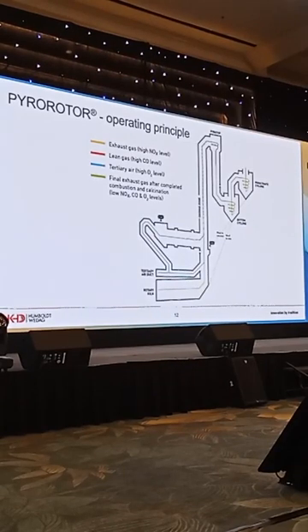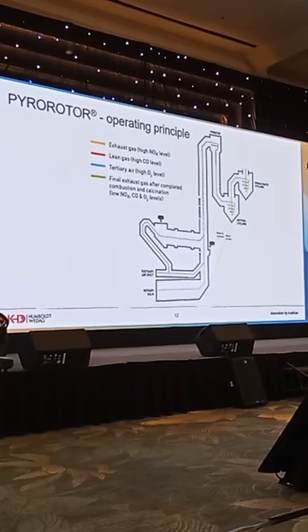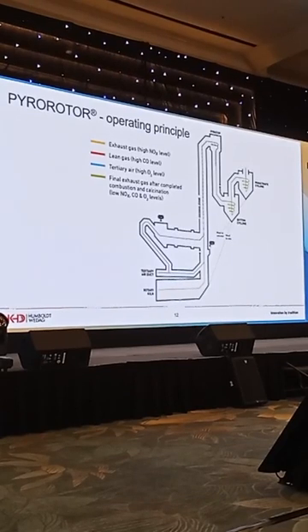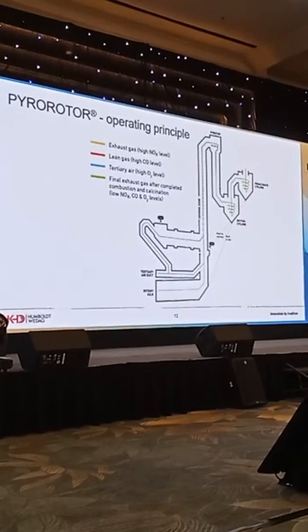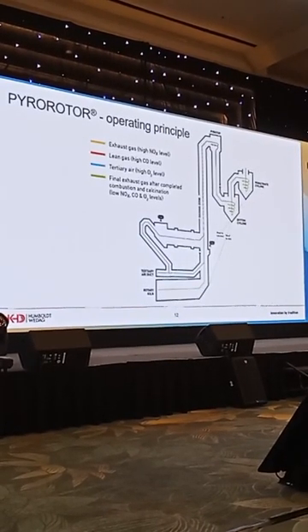And here in the remaining calciner, the CO-rich gases give their heat to the meal fed from the existing cyclones, so the heat is transferred and used for the process. On the other side, the CO-rich gas reacts with the NOx-rich environment coming from the rotary kiln. So at the end you have a good combination of burning the alternative fuels, having the heat transfer to the system, and also reducing the NOx emissions to a certain level in the existing system.